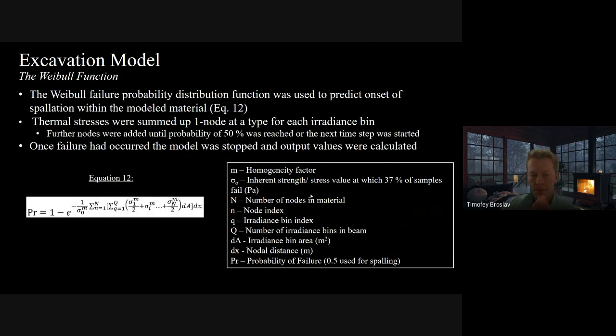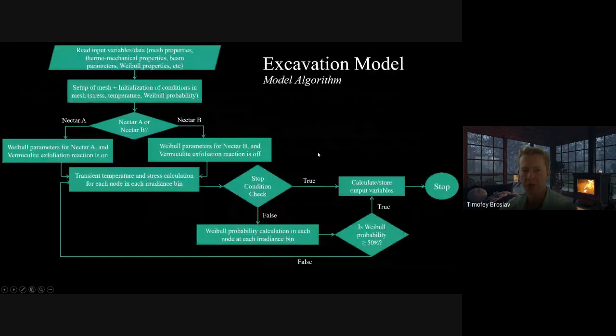Now, the Weibull function that we used to simplify the fracture propagation modeling, we had to sum it up in essence due to the fact that we had a two-dimensional thermal stress array. So thermal stresses were summed up one node at a time for each irradiance bin, and you would add further nodes until the probability of 50% was reached. So let's say the surface node was solved for each irradiance bin, and then the subsurface node was solved if 50% probability wasn't reached for each irradiance bin, and so on. And the model was stopped once a probability of 50% was reached.